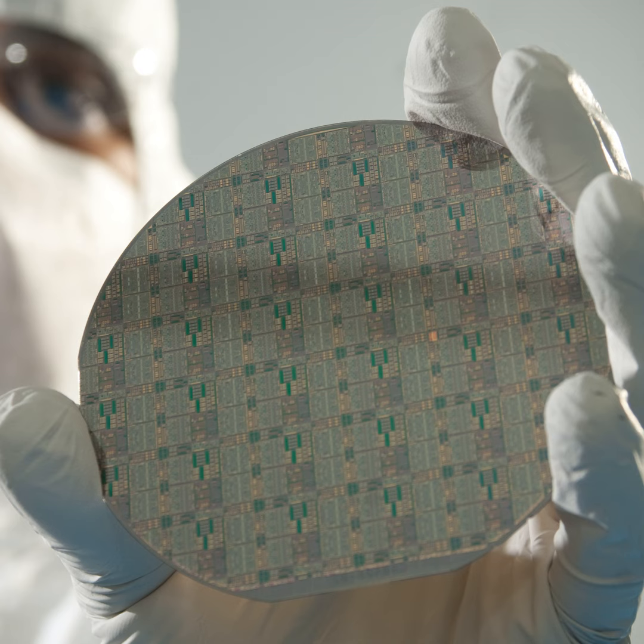We will have some of our standard electrical testing that we do day to day on our circuits and transistors, things like IV curves and RF load pull at X band on both the transistors and the circuits. And then on the thermal side, because as I mentioned, NJTT and ICECool created the foundation for thermal measurement techniques, we'll be using things like steady state thermoreflectance and time domain thermoreflectance. These will help us characterize the different planes of the diamond to ensure that our models and measurements are correlated well. Gate resistance thermometry and Raman will also be used to measure the diamond itself and the surface of the transistor, so we can see as close to that hot spot as possible in our transistor.